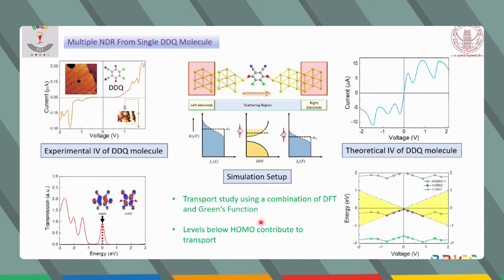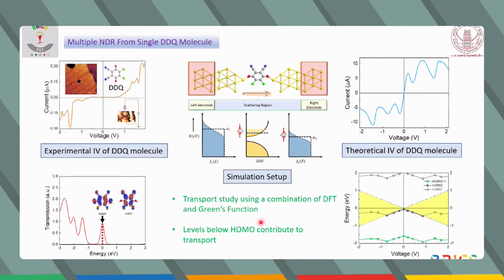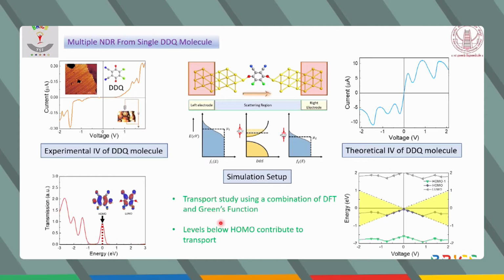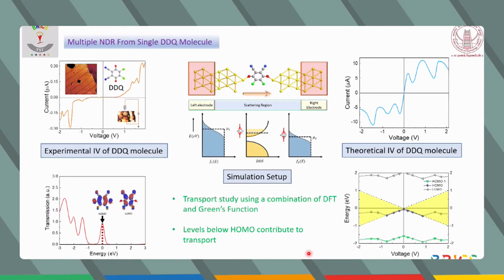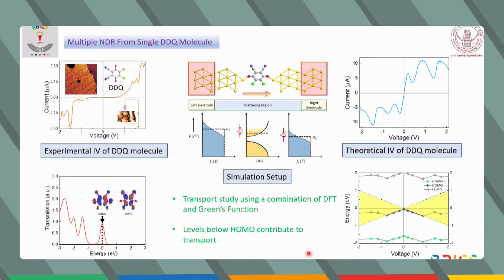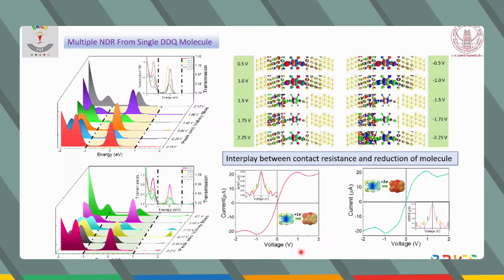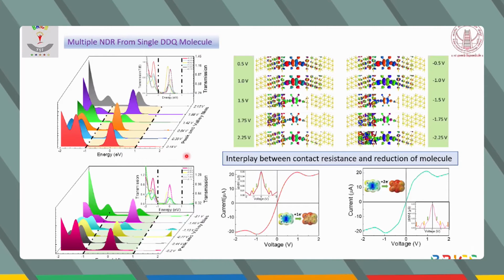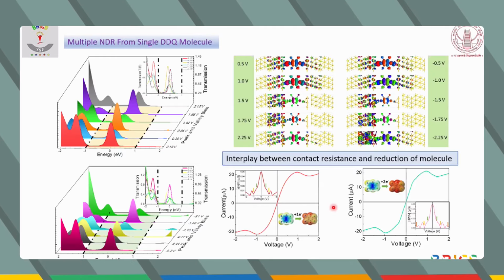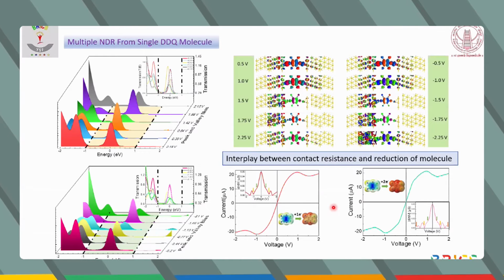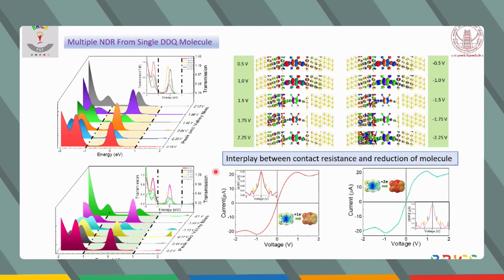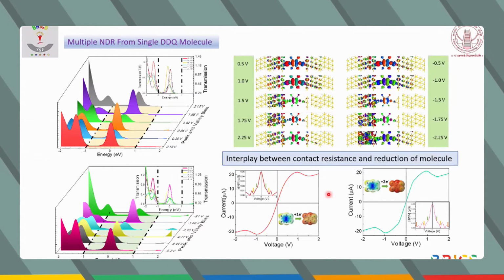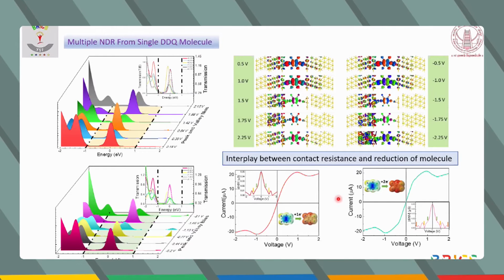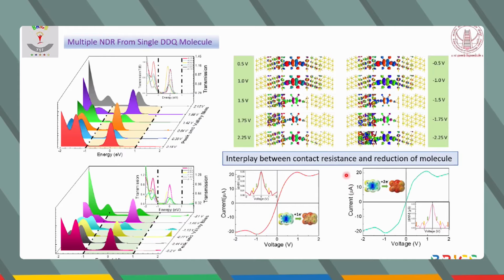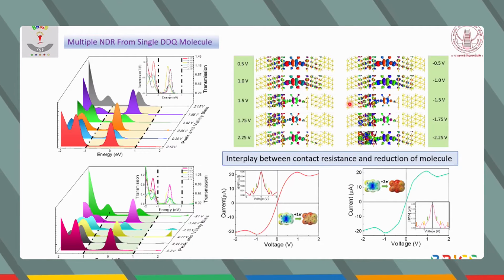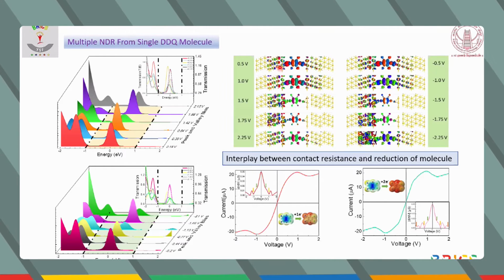When we studied the transmission through the molecule, we found that the energy levels below the highest occupied molecular orbital are the ones contributing towards the transmission, or the transport of the charge. When we studied the transmission very closely, we found that this behavior of multiple NDR on the positive and negative side is because of two reasons. One reason is that the molecule is reducing, and only at some specific voltages. There is another factor that is also responsible for this behavior, and that is the contact resistance between the molecule and the gold contacts.